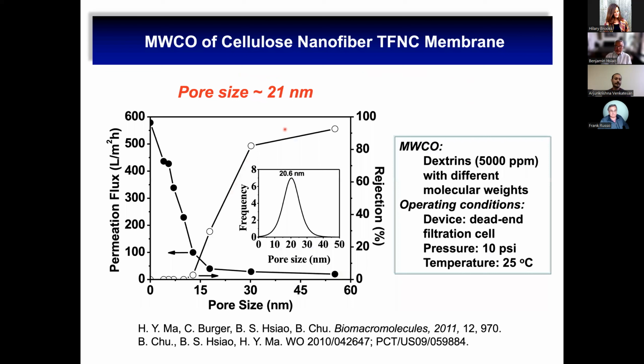And indeed, we used a molecular cutoff experiment. Molecular cutoff means we use some macromolecules of different molecular weights, and we use dead-end filtration to compare the flux with the different molecular weights. We can convert the molecular weight back to the pore size. It's a simple conversion between the radius of gyration and molecular weight. So we estimate that at the 90% rejection rate, we have a pore size of about 21 nanometers or so.